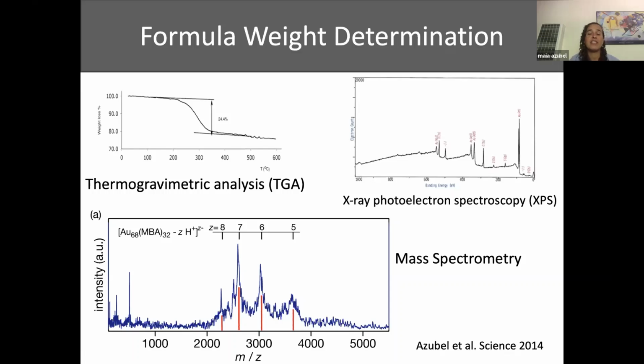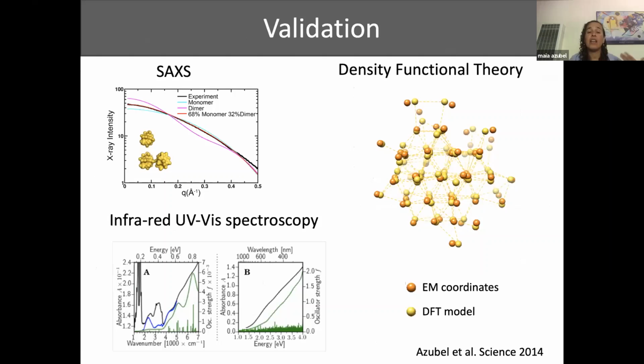So after the structure was solved, we did a lot of validation. Part of the validation was done at Berkeley. Greg Hura did the SAXS. Hannu Häkkinen and his group did the DFT. Mika Pettersson and his group did the infrared and the UV spectroscopy. And it was very nice to see what you are seeing here. In orange are the coordinates from the EM, and in yellow, the coordinates from the DFT, so we have the validation of these things.